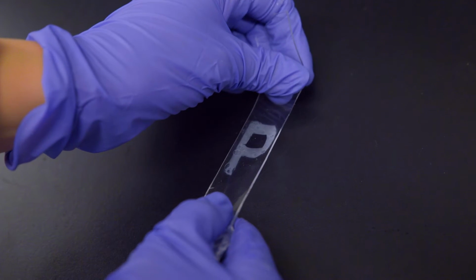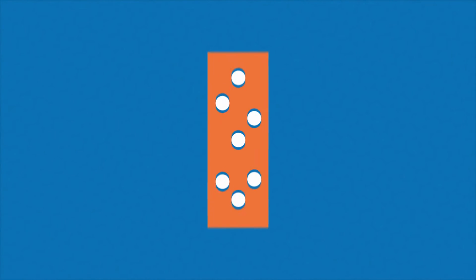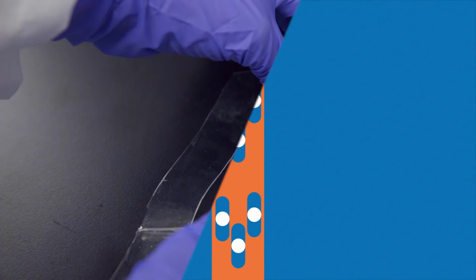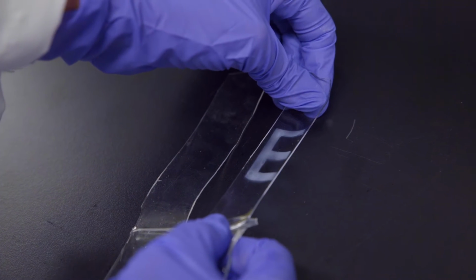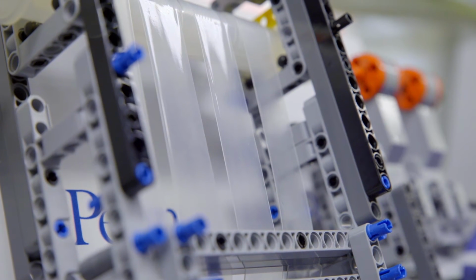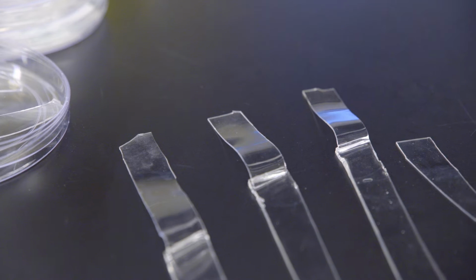Silicone, as you know, is very rubbery. You can stretch them many different percentages, but silica doesn't move. So in this case, we actually create air pockets between the silica and silicone, and all of a sudden you started to display your original color change and the transparency change. The whole idea is changing the color or changing the transparency.